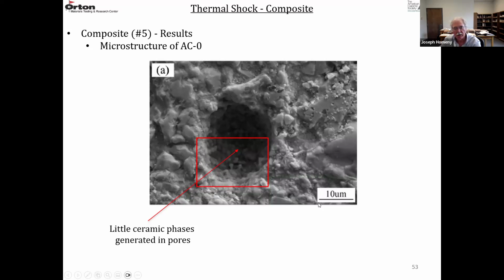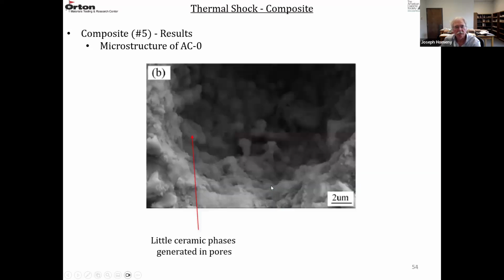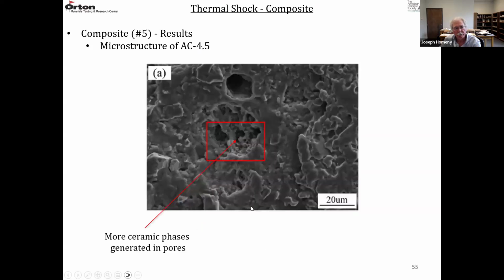We're looking at a higher magnification. Not much happens here on the surfaces. There's some ceramic phases generated, but not to a great extent. And this is just a higher magnification of AC0. You can see some particulates forming. So there's some phases starting to form in the pores. It's actually forming everywhere in the microstructure, but you can see them more easily on the pores.